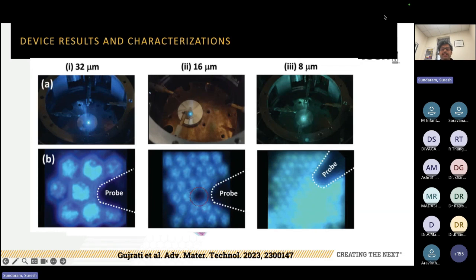And when you change the feature size from, let's say, 32 micron to 8 micron, that means 4 times lower, you can see that your emission wavelength is also changing. Here from 460 nanometer, you go to 490 nanometer, which is cyan. But normally by changing the feature size, you can go much lower also. You can go up to green, and we are trying to reach red using the same process.